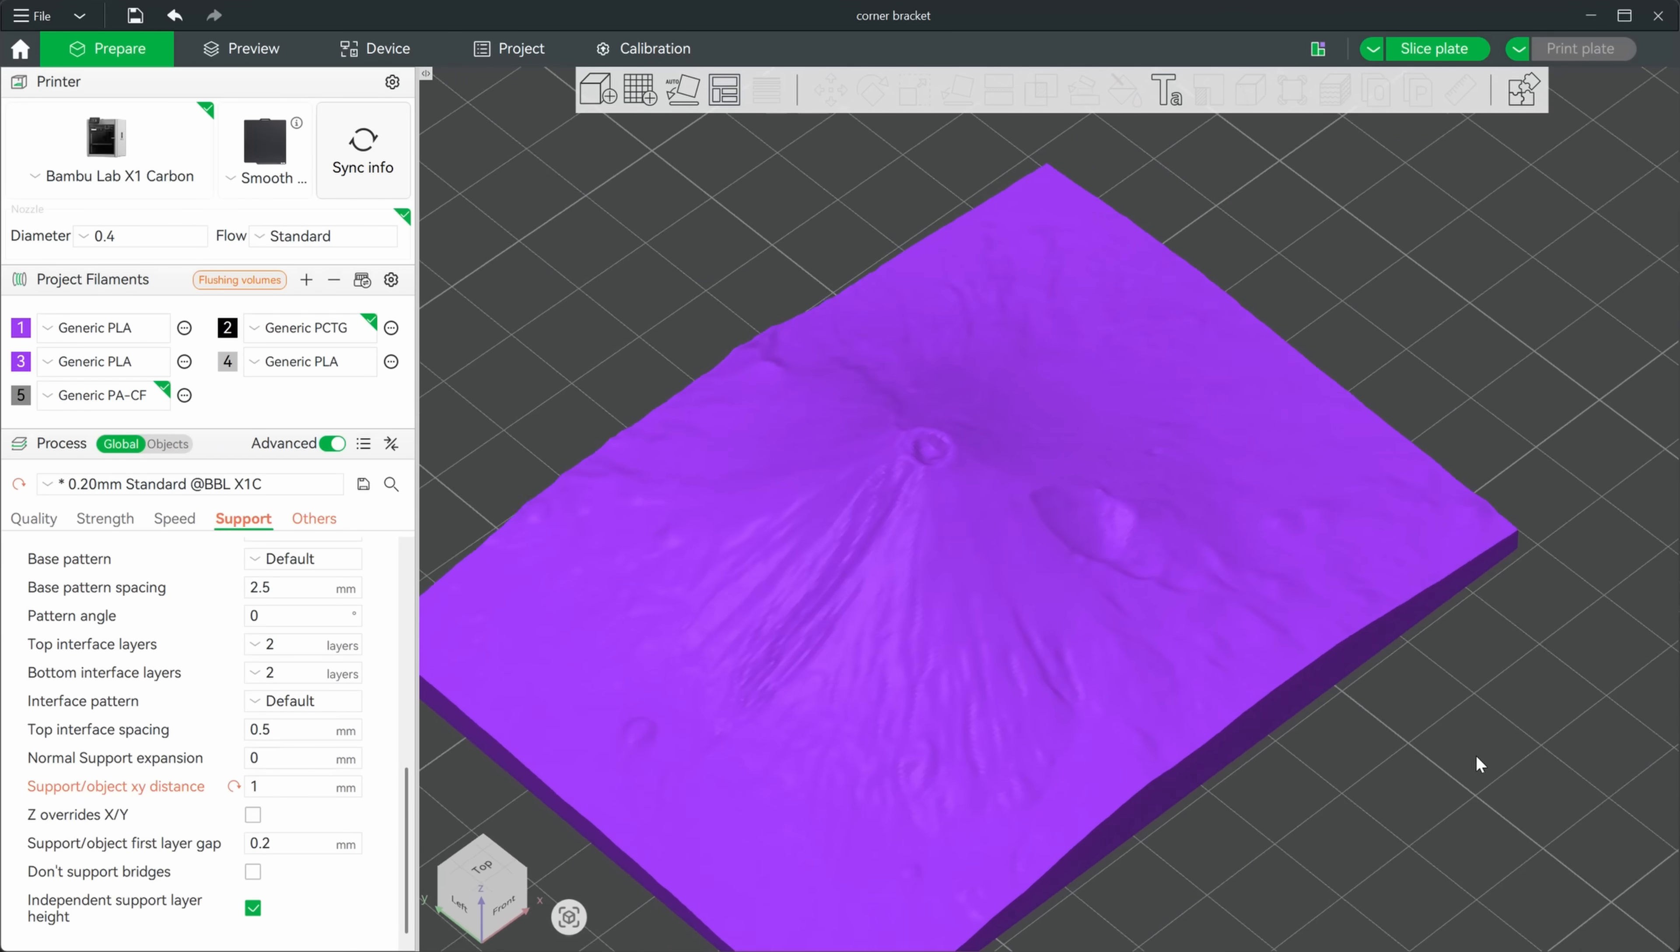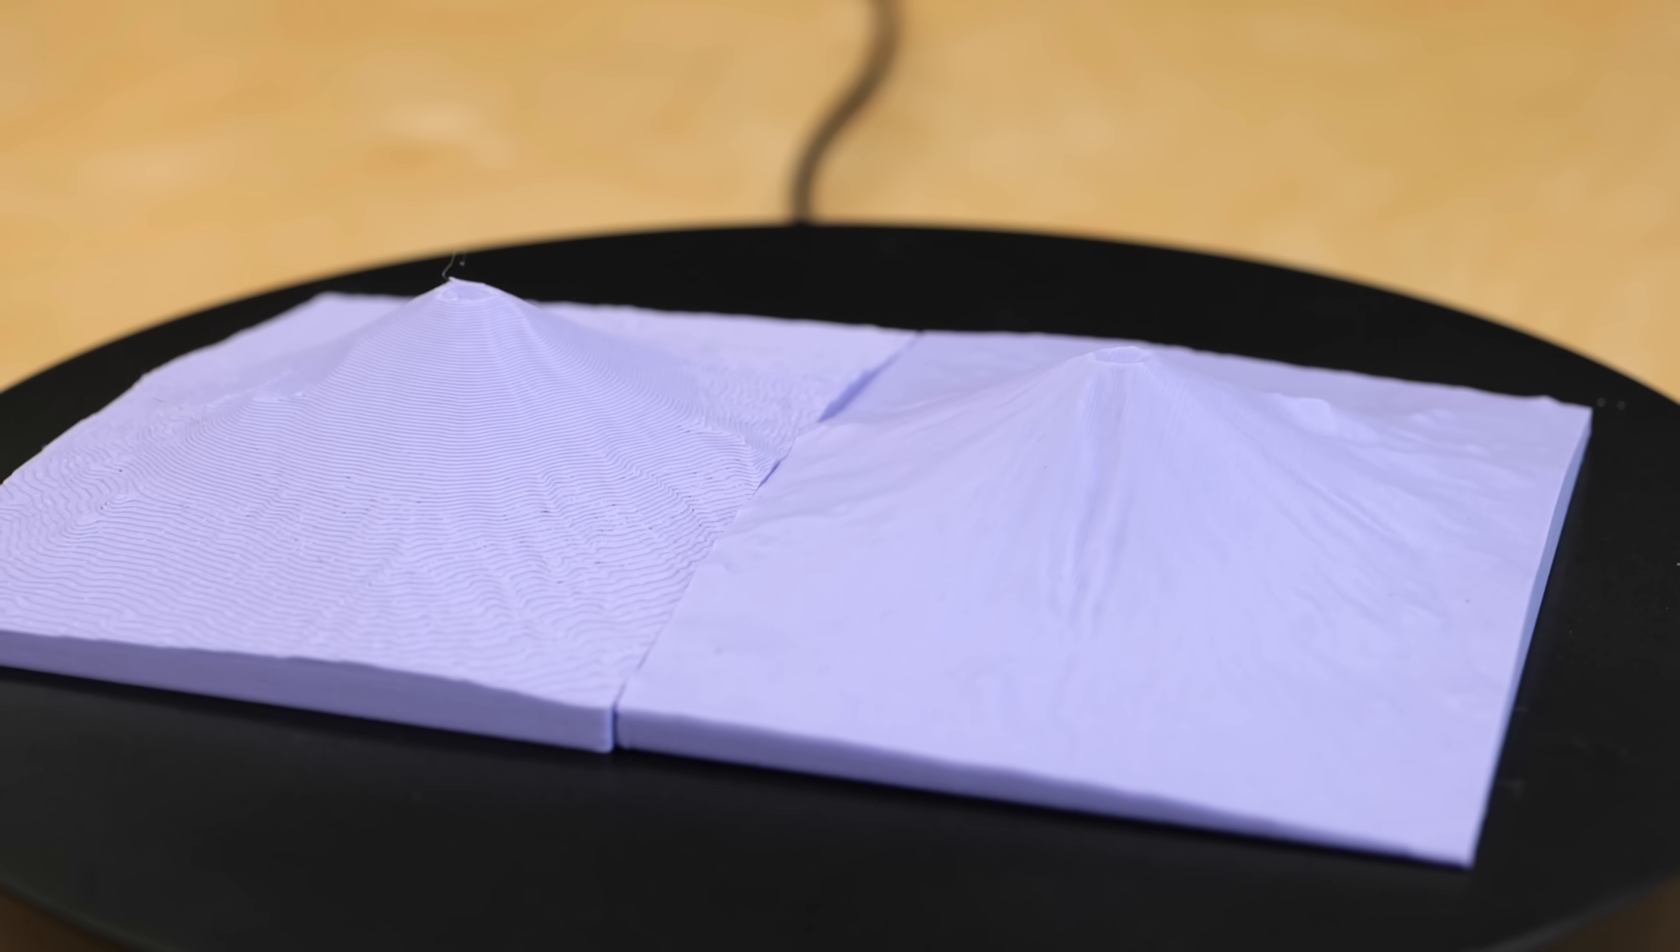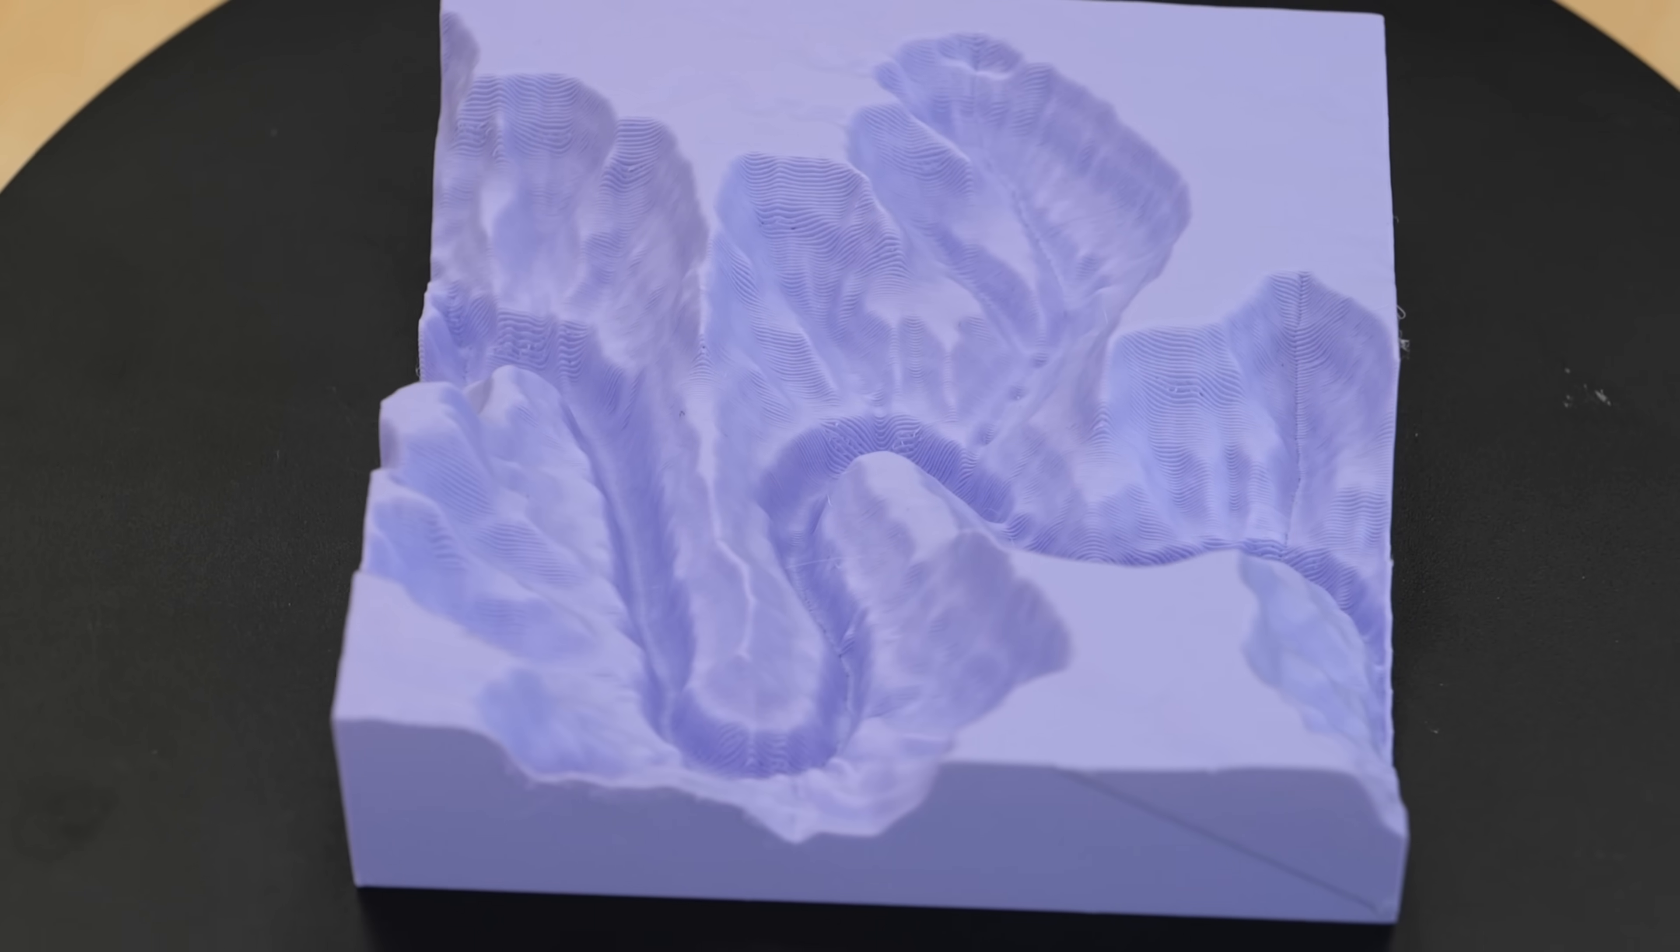Just look at this relief print of Mount Fuji. One version is printed as it loads into the slicer and is also the way the author printed it, but that orientation leads to significant stair stepping, especially on shallow slopes. If we tilt the part 90 degrees on its side, it still prints great and produces a buttery smooth surface even at 0.2mm layer height. This has a limit of course, but as long as the slope angle stays below roughly 45 degrees, everything's fine. Anything much lower and the perimeters start printing into thin air or you'll see exposed infill. But you'd be amazed at what a 3D printer can do with good cooling and good materials.